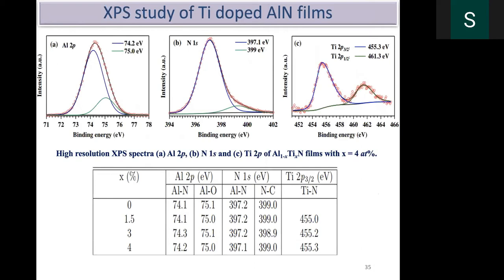We just wanted to see whether oxygen is there in the system or not. We did XPS. You can understand from these data points and this profile, the predominant peak is at 74.2. That means aluminum nitride is there. The aluminum oxygen content is very, very less. This shoulder only shows a possibility, because sputtering takes place at around 10 power minus 3 millibar vacuum.